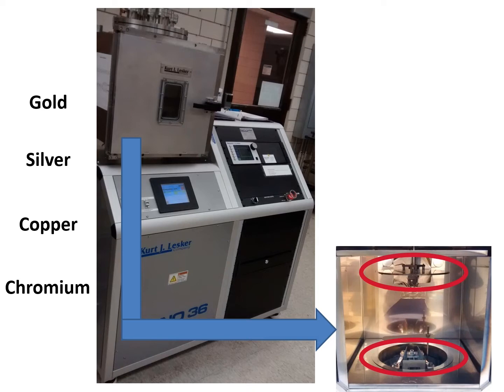The system achieves high vacuum via a turbo pump, which is backed by an oil-based roughing pump, and is capable of achieving vacuum in the 10 to the -7 torr range. In a typical process, the chamber should be pumped down to 5 × 10 to the -6 torr, and typical deposition rates are 0.5 or 1 angstrom per second. If your samples are sensitive to X-ray radiation, this system will be a good choice for the deposition process.